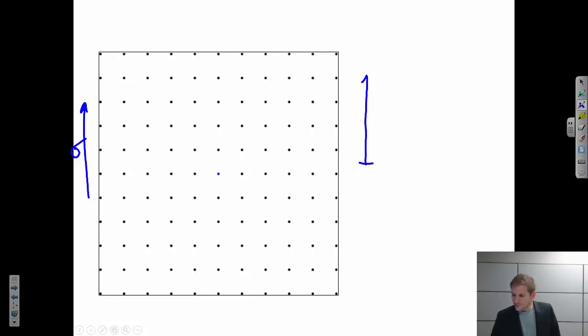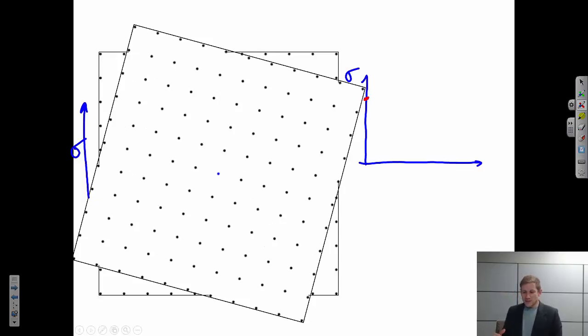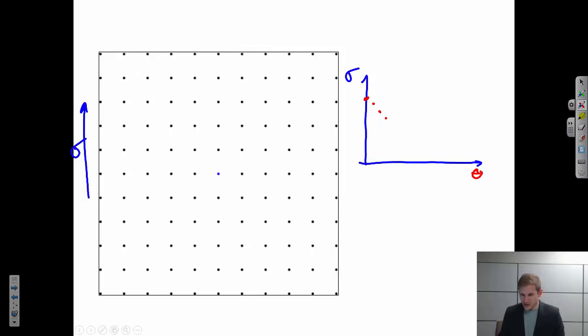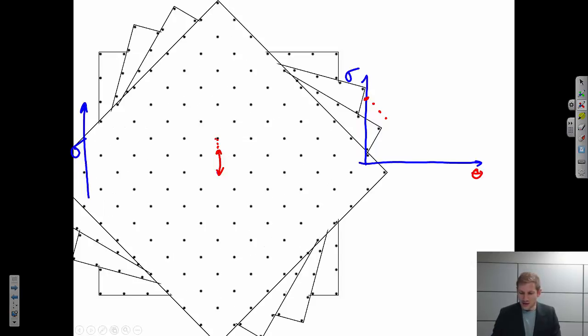So I can make a graph and plot the electrical conductivity of that point here. So let's do the same thing, but let's rotate the lattice again. Now I'm still measuring in the same original orientation. So all that has changed is the rotation angle of that lattice. And in this case, maybe the electrical conductivity has decreased a little bit. And I can measure that again and again and keep rotating it each time. And I'm going to get a slightly different value for that property because the structure of this lattice is different in those cases. And so you'll see I went from originally having a very close spacing between neighboring lattice points to something where I had a much greater spacing between the lattice points. So maybe that's why I'm seeing a change in the physical properties.